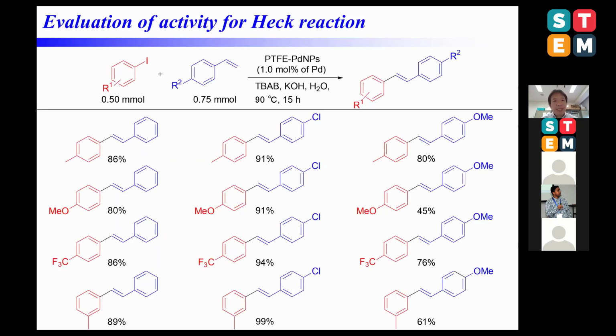And we next investigated the catalytic activity of PTFE-supported palladium nanoparticles for the Heck reaction in water. A variety of aryl iodides was successfully coupled with styrene to afford the desired product in good yield. Although the coupling product was obtained in excellent yield from the reaction with 4-chlorostyrene, a moderate yield was observed in the case of 4-methoxystyrene.